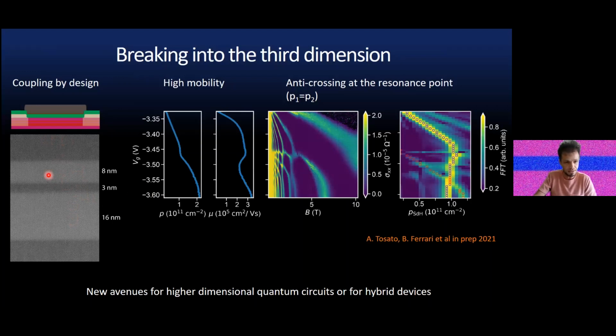So here you see a really beautiful cross-section image of a double quantum well. In this case, it's still our first devices, so they're contacted together. They are designed in such a way that the bottom one is thicker and the top one is thin, so that by design, with only one electrode, you can progressively populate the bottom quantum well and then the top quantum well. So this is by design, and then we actually did the experiment, and here I present this result really from Alberto and Beatrice, who have been working hard on these measurements over the past 3 to 4 months.